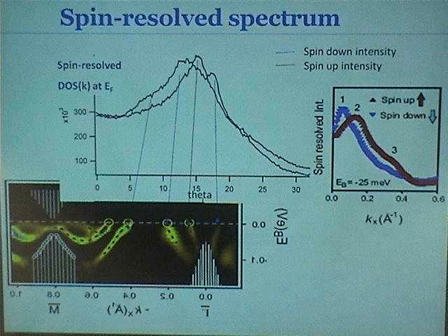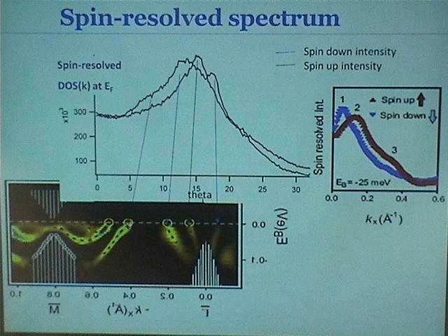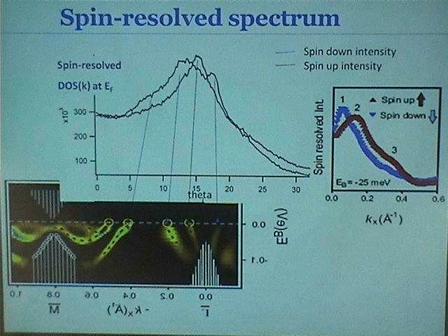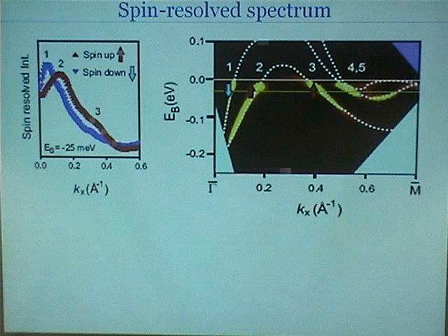Yeah, but this is Mott scattering, right? So even if it's 100% polarized, you don't... Yeah, this is the Sherman function. Because of the Mott scattering. That's what I meant by you already have a background to start with. There should be nothing there, but there is a lot of intensity there. How selective can your detector be? How much more do you get in one channel than the other? Could it be split polarized equally? So I'll show that in antimony, where the system is cleaner. Okay.